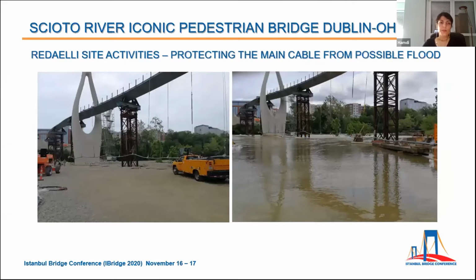Well, during the cable installation, a strong rain significantly raised the level of water in the Scioto River, and it caused a flood and subsequently stopped the site activities for several days. Thanks to the quick thinking and immediate action of personnel on site, suitable wooden support was prepared before the flood hit. On the river side, the wooden supports were not enough. Therefore, the main cable has been hung to the deck, keeping the cable above the water to avoid possible damages.